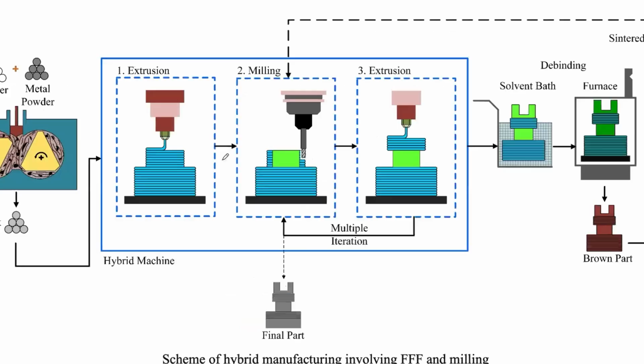A good thing about this particular structure is that you can also do hybrid additive manufacturing, so you can do additive and subtractive manufacturing together. While you are printing the part, at the same time there can be something like a milling setup embedded, and this milling setup can mill out the parts which are not desired, and then again the extrusion can happen on top of the part. So you can do this hybrid additive-subtractive manufacturing, and then once this happens, you put it into a solvent bath, do solvent debinding, and then you do the thermal debinding and sintering, and you get the final sintered part. So this is another philosophy that you can look into. Now, I told you a few slides ago that this is not something that I invented.